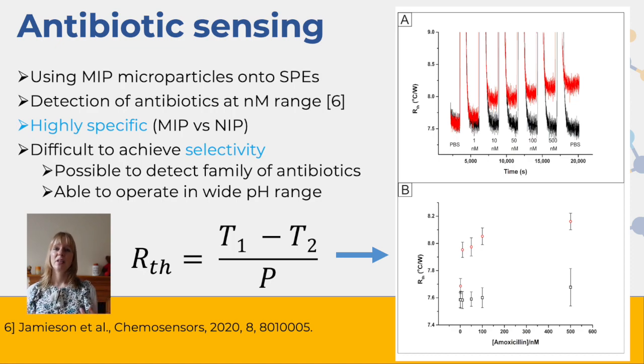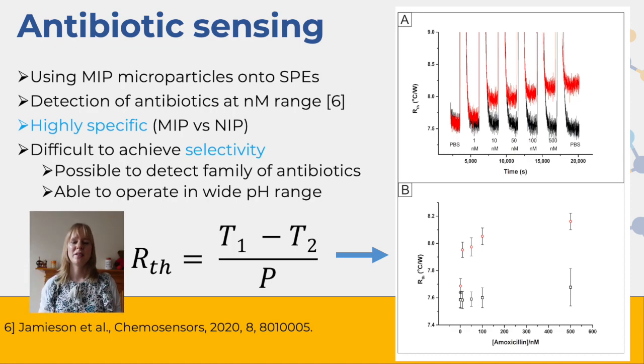Now, just look at it here. You can see that as soon as we start to increase the concentration of this amoxicillin, there was an increase in the thermal resistance for the molecularly imprinted polymer, which is depicted in red. And the thermal resistance we define as the temperature gradient, which is first of all the temperature that you impose on the system, which is in almost all of the cases 37 degrees, versus the temperature that we measure, that's T2, over the power that you need in order to keep it at a fixed temperature. So under ideal conditions, the temperature that we keep it at and the power are exactly the same, they are fixed. However, if you start to inhibit your heat flow due to binding in your polymer material, we would expect the temperature to go down. So as a result, your thermal resistance will increase. And that's exactly what we see here.